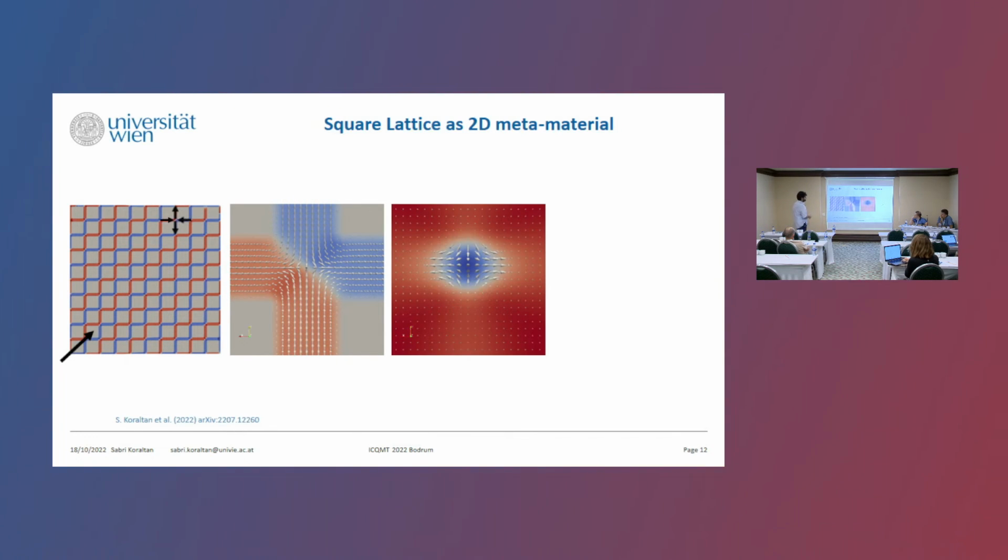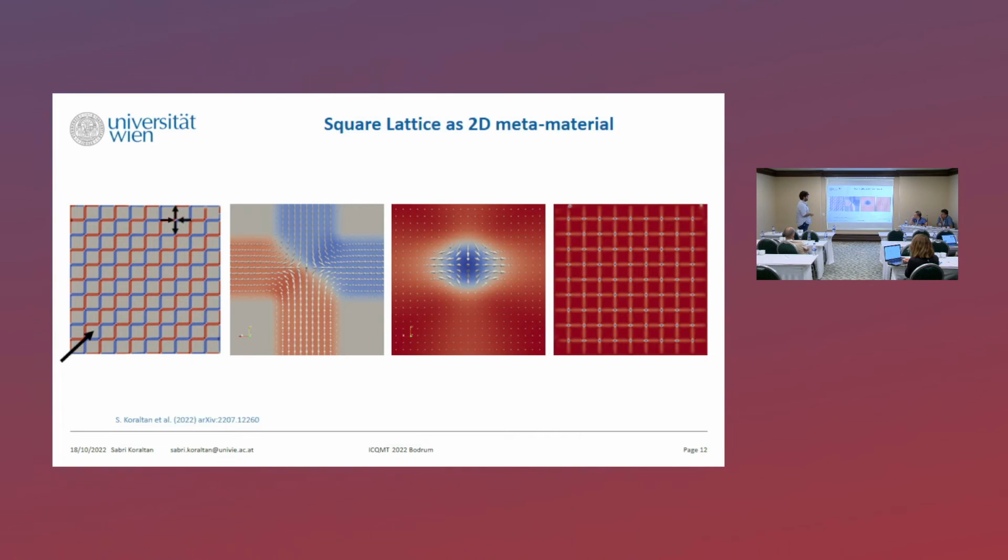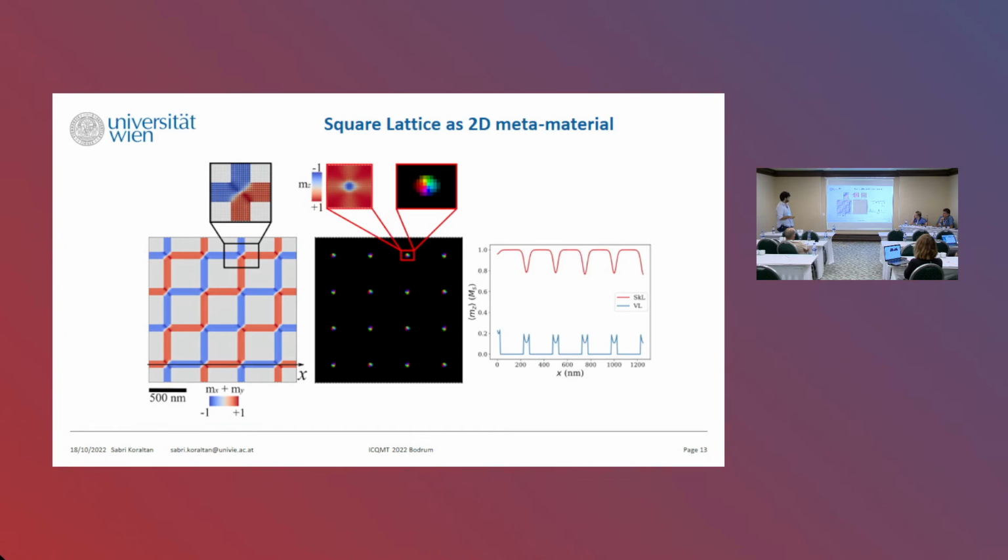And the goal was to obtain the antiskyrmion underneath, which we can see here, again, exactly wherever we have the anti-vortex core. So we're making use of the exchange interaction to imprint a little bit, or help to nucleate the antiskyrmions. Again, we can choose the direction by the sense of rotation. As you can see here, the antiskyrmions are rotated by 90 degrees, which might actually be helpful, but I will give that information later.